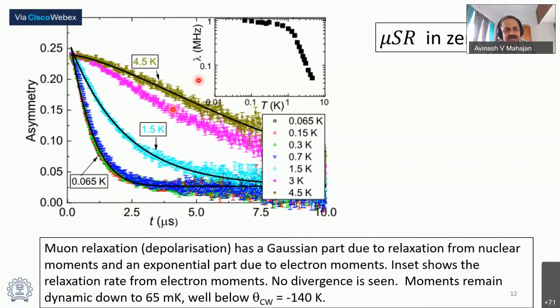Okay, so that relaxation rate, so to cut out all the detailed analysis here, one finally obtains, based on the exponential relaxation of the muon depolarization as a function of temperature, this lambda muon relaxation rate as a function of temperature. And one sees that there is a slowing down. So one sees a relaxation rate increasing, but then it levels off at low temperature.